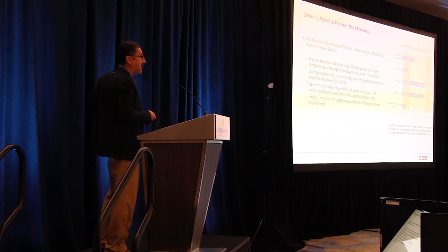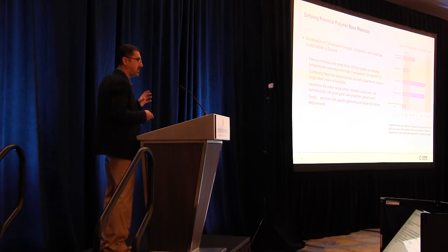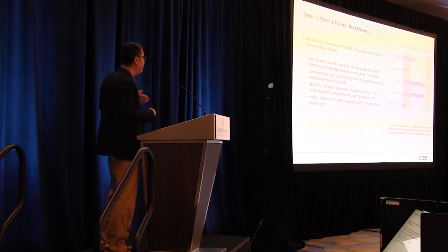But at the other end, at the extreme end, we have to be concerned about the sealing efficiency. Now, you are going to be working with very high stiffness materials, which may not be a good sealing material because they may not have enough elastic response. So they may be too stiff, too hard to seal a gas like hydrogen. So we are in the process of defining these limits, these boundaries for all of these grades. So this is just a random representation of the optimization game here. But again, the higher numbers do not necessarily mean these are the best materials yet, but we are working on that part.